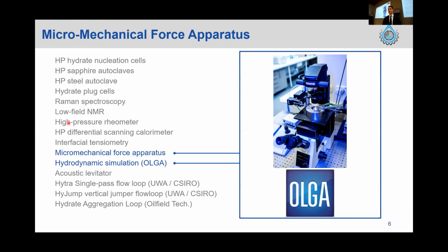So just to talk a little bit about the apparatus that this research was performed on, most of it was performed experimentally on the MMF apparatus, which you might have heard a little bit about before, but I'll just briefly talk about in the picture here. So we have a microscope with a recording device, which is basically recording everything that happens in this experimental cell here, which contains the cyclopentane liquid, which is a hydrate former for these experiments. And that is surrounded by a metal cooling jacket, which is just used to cool that experimental cell to the desired temperature for the tests.